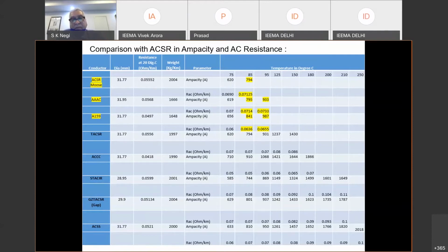It is a well-established fact that a 400 kV line, even in load dispatch centers, is limited to the extent of 400 or 450 amps, and it is not loaded beyond the surge impedance loading. Surge impedance loading of the 400 kV line itself is about 500 megawatt. So we have to think of a conductor which can carry better megawatt with the same sag and same tension positions in the existing tower or a new tower design.